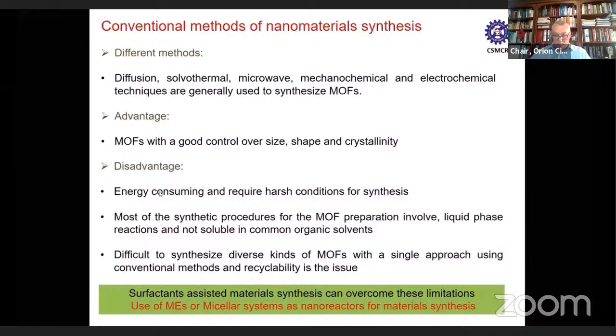These methods are very energy consuming and require harsh conditions of temperature and pressure for the synthesis. And most of the synthetic procedures for MOF preparation involve liquid phase reactions and are not soluble in common organic solvents. So it is difficult to synthesize different kinds of MOFs with a single approach using conventional methods, and recyclability is also an issue with these methods.